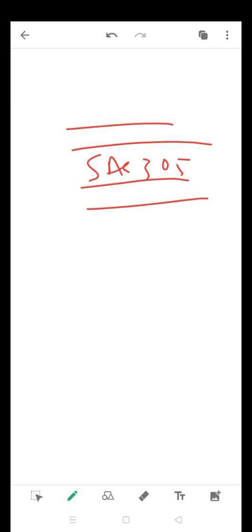So it has been found that the crystallite size in the case of the layered samples was much less compared to the non-layered samples. This is mainly because of the extra thin layer that we have introduced on both sides of the solder joint; that thin layer prevents any sort of major diffusion taking place. So say this is your SAC305, and you have a tin layer above it, Sn. Above that you have copper.